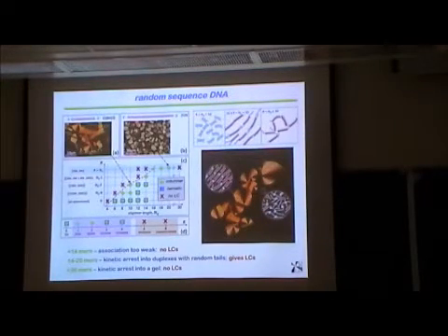Well, what you find is that you make oligomers of various lengths and look at solutions. If they're less than about 14 base pairs, there are no liquid crystal phases. But in a range of about 14 to 20 base pairs, you get liquid crystal ordering, and for longer random oligomers, you don't.